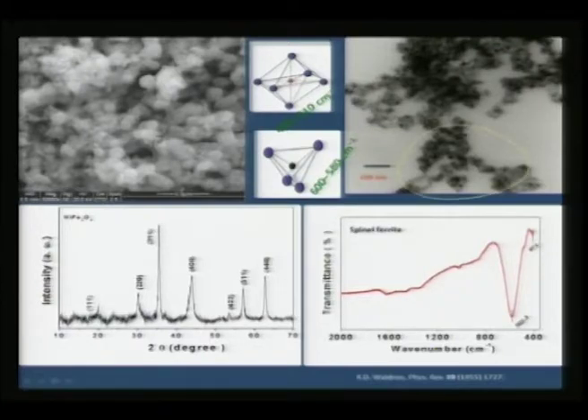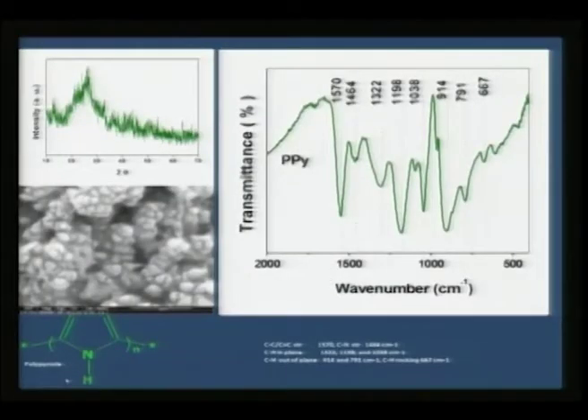You can see the TEM morphology of these nickel ferrite nanoparticles, and you can see the SEM of the nanoparticles, and they are more like wafer clusters of oxides which are present, and typically you can see the iron oxide stretching frequency which is characterized by this, and also the spinel pattern which is emerging from the XRD. So, all we can clearly say is that we have a clear proof that we can make nickel ferrite nanopowders, and similarly we can make polypyrrole out of sonication.